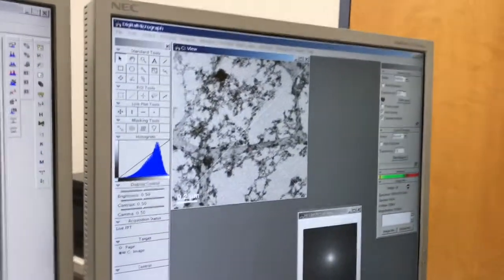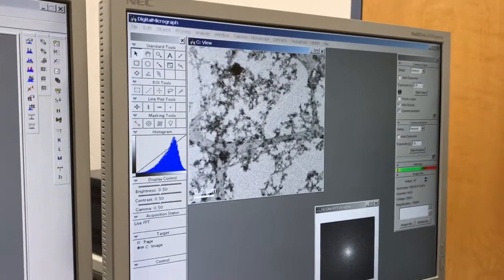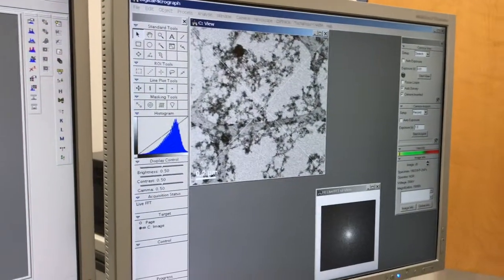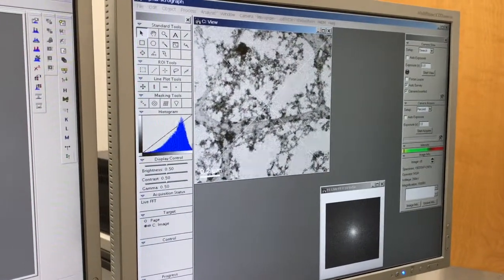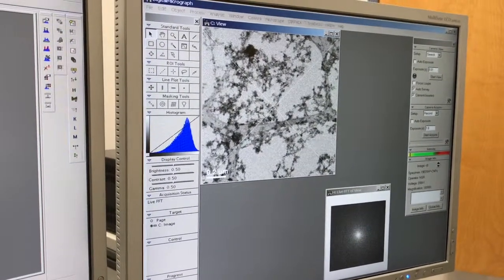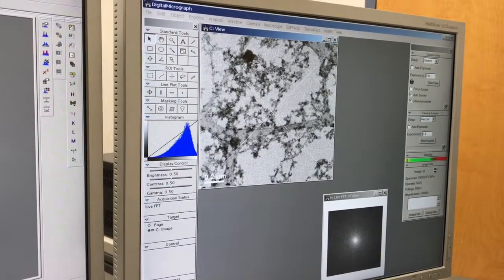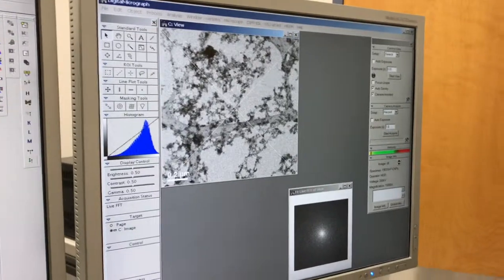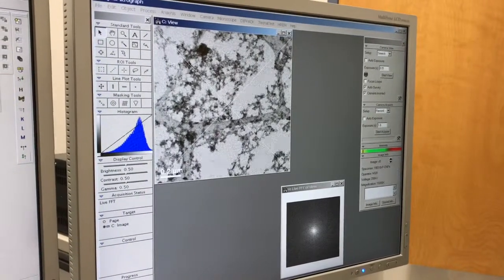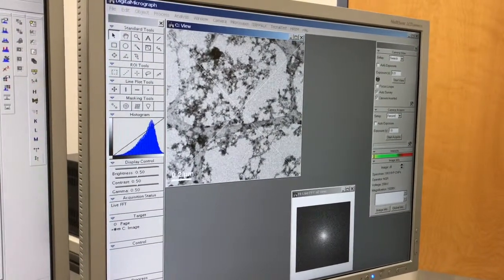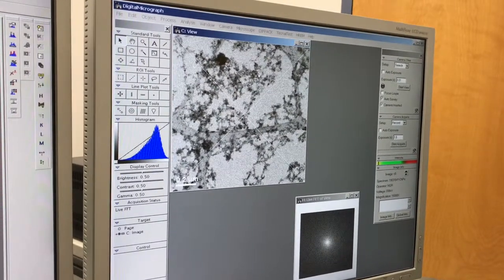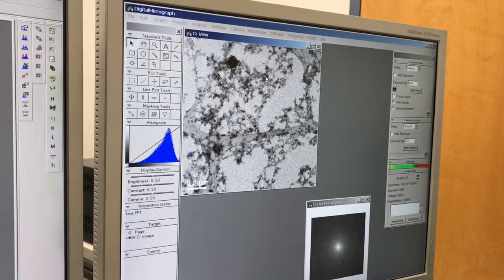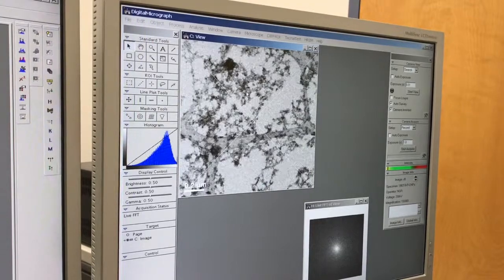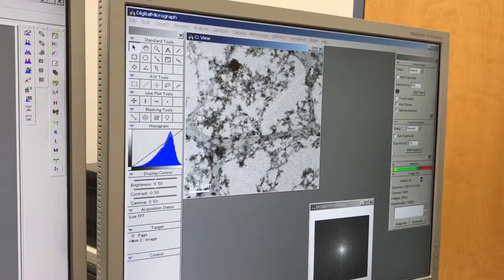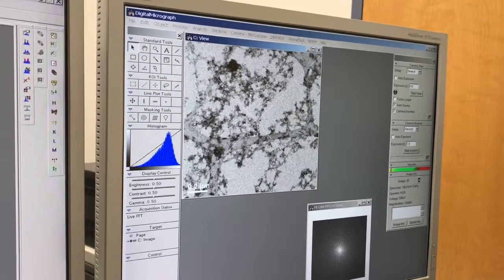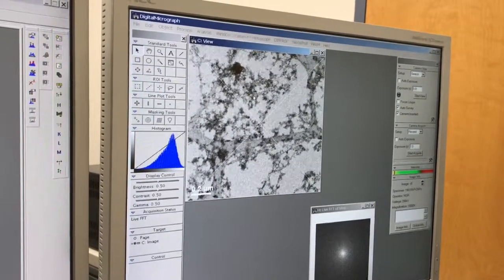So the key parameter when you're live imaging is the exposure time, and that literally is how long your camera collects signal before it generates an image. So right now it's only collecting signal for 1/100th of a second before it generates an image. So the exposure time in general, if I increase it, is beneficial in the quality of the image.